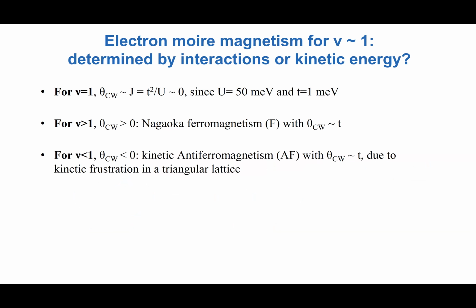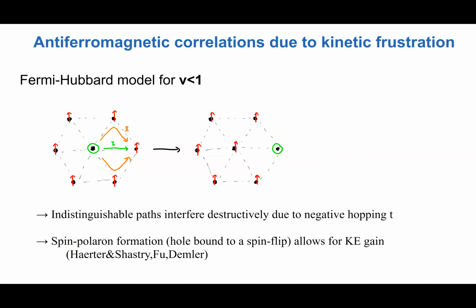Okay. Now, how about the smaller than one case? Here the physics is more interesting. I will not dwell too much on it because this regime is not very accessible in the experiment. But this was analyzed by Haerter and Shastry in 2005 or so. So basically, this is a triangular lattice with kinetic frustration. What that means is that if you have spin polarized electrons, then the hopping experiences a destructive interference because of the negative sign of the hopping. This destructive interference can be avoided if each hole has an associated spin flip. So I'm not talking about the ground state now, but if I apply a finite magnetic field, how would the magnetization change? This really suggests that the system would act as if it prefers an antiferromagnetic state, and there would be an obstruction of full polarization.